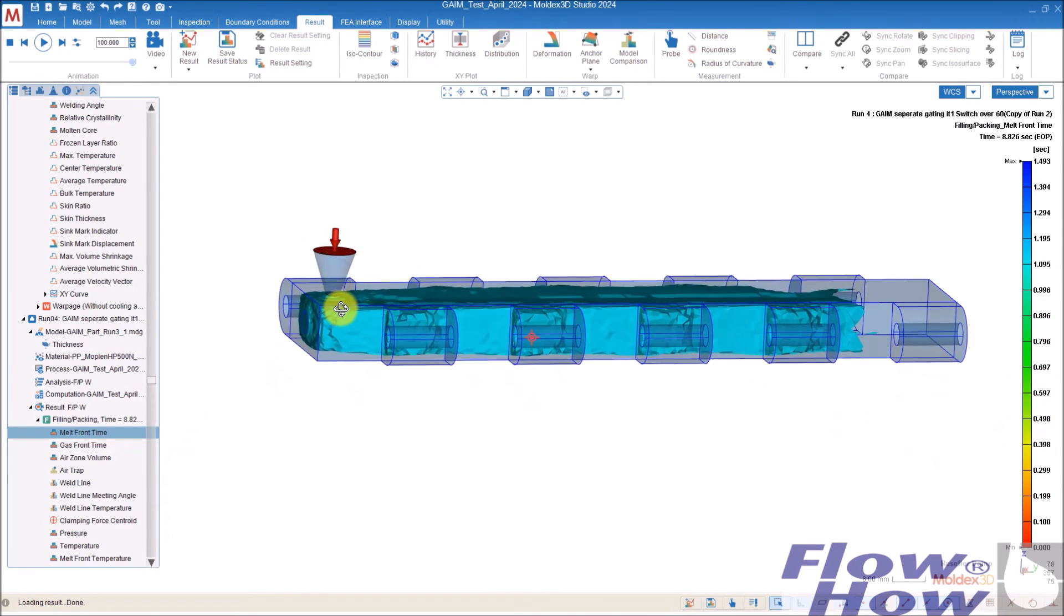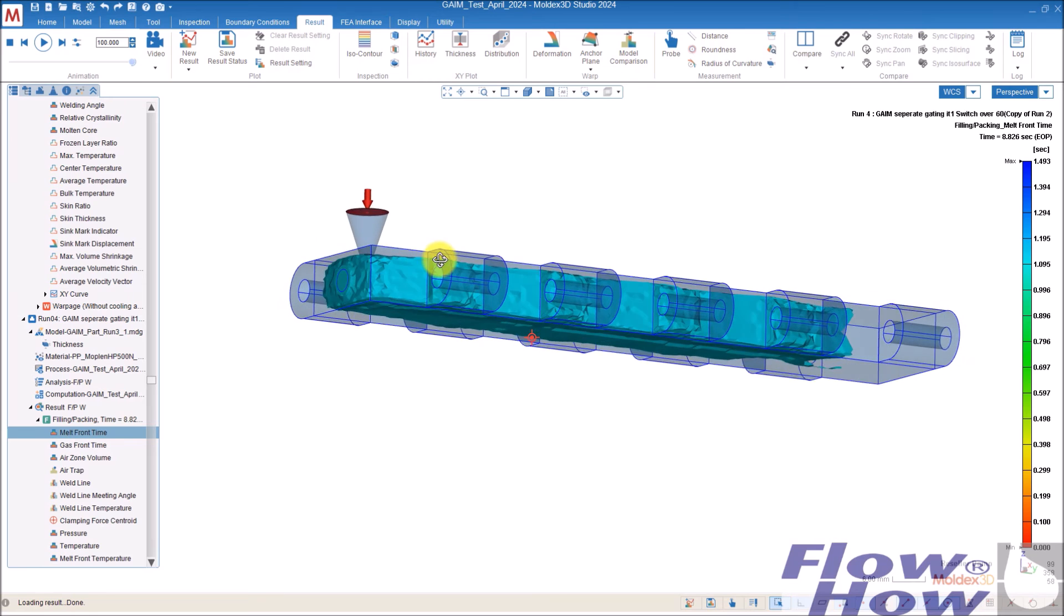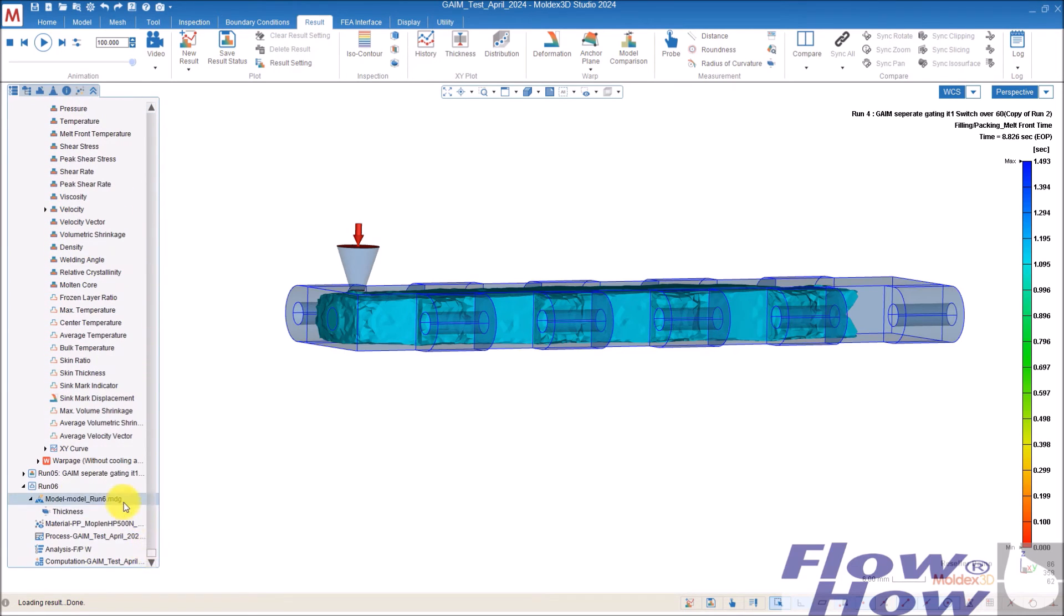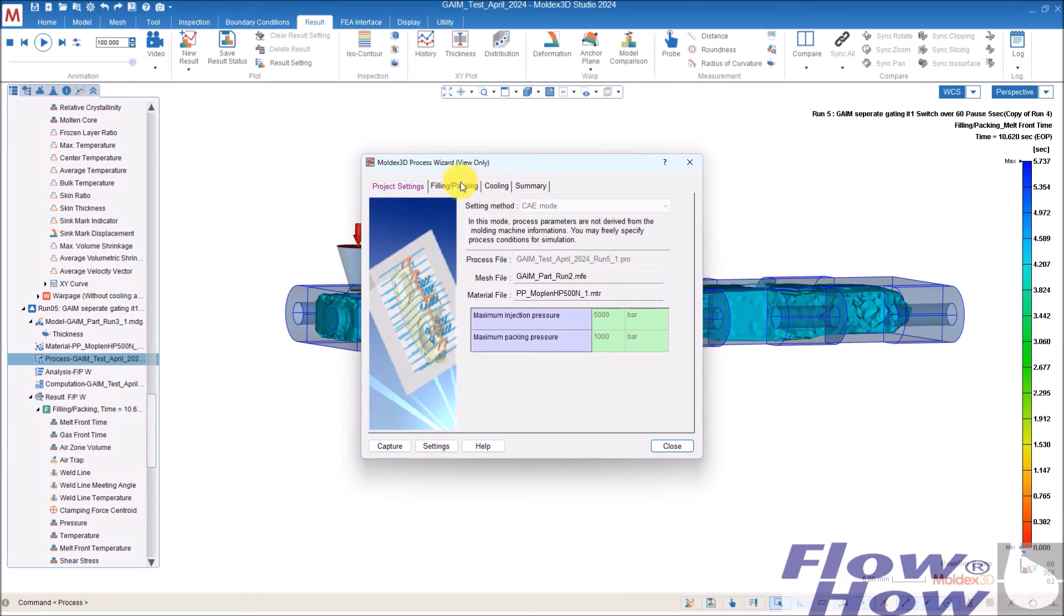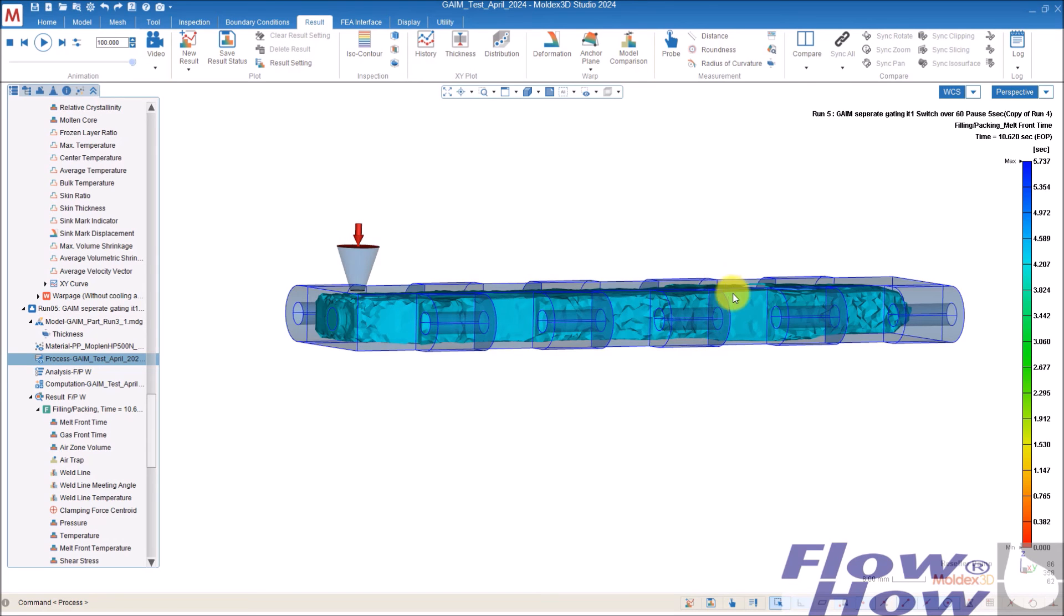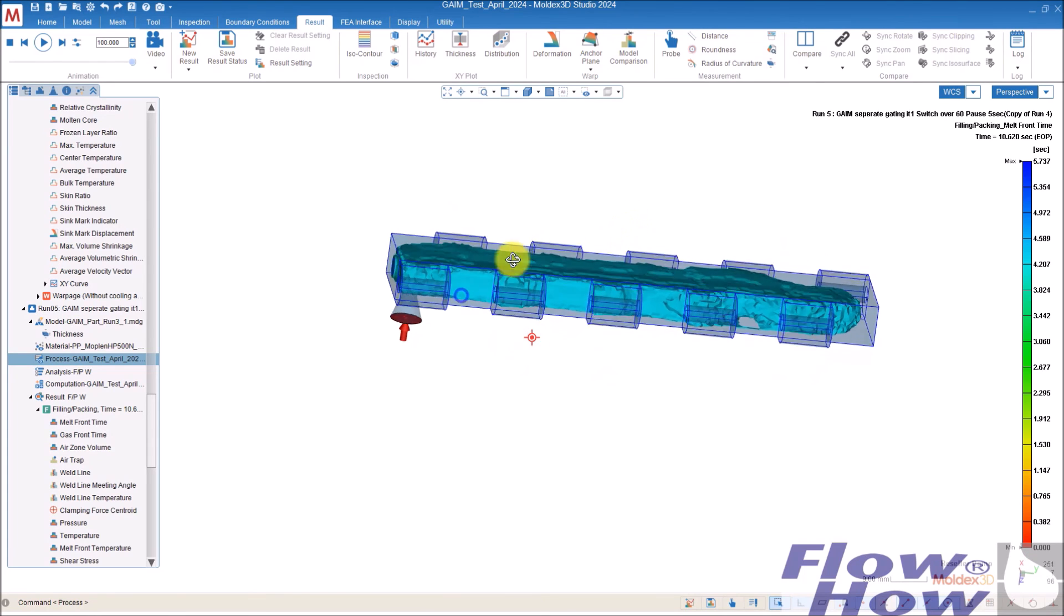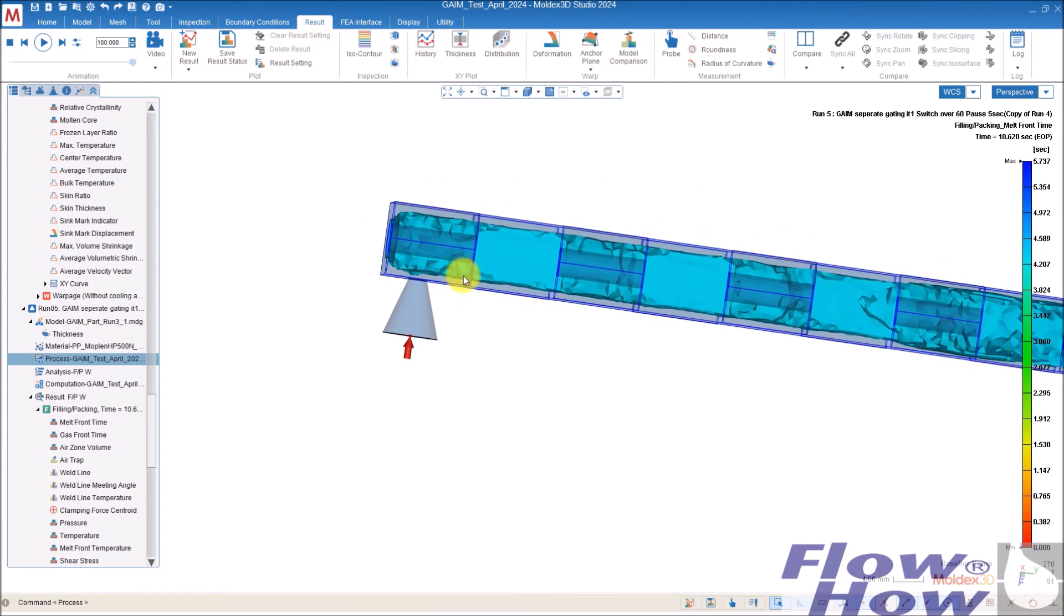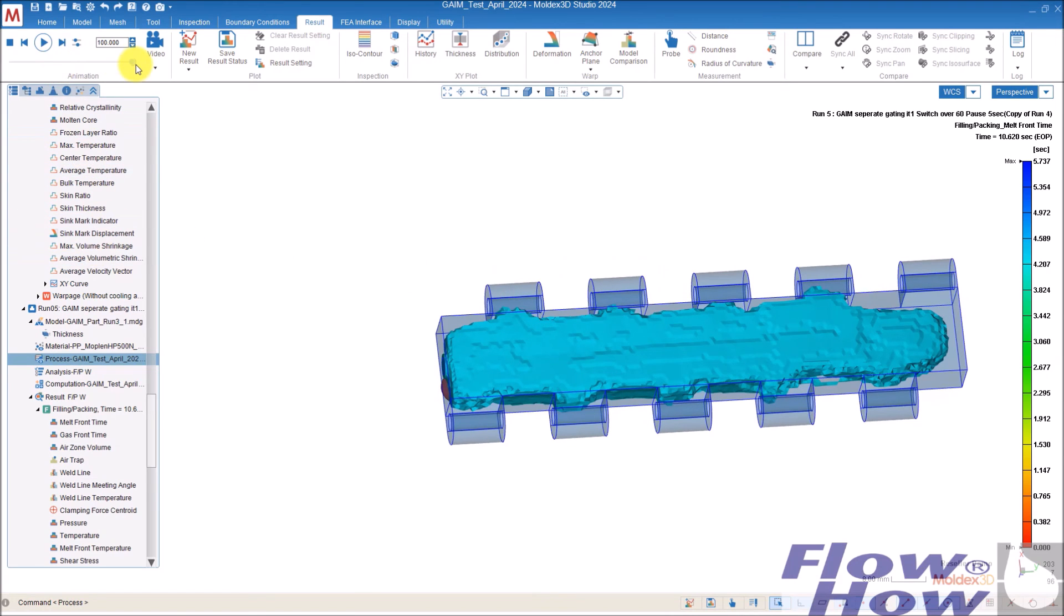And then I tried with a 60 percentage and I ended out something like that. But you can see here, I have a problem around this gate. So I thought, okay, I need a bigger, a thicker skin. So I put in a pause time of five seconds. So I have the injection and then a delay and five seconds after I start blowing in. Of course, you can do that with such a thick walled part. But now you can see the skin thickness is bigger. And I actually ended out with quite a good.